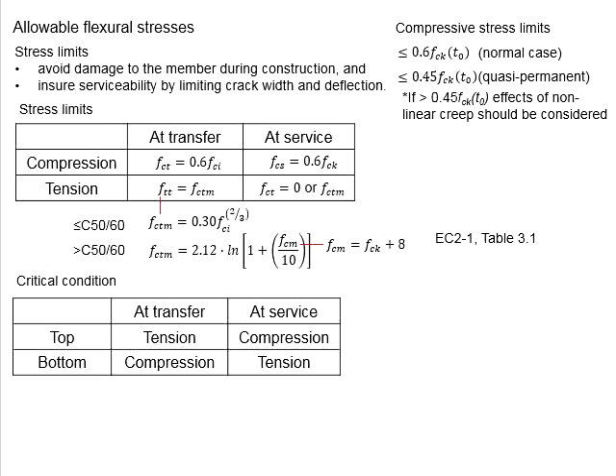Excessive cracks on the concrete will significantly affect the performance of the pre-stressed concrete structure. Before we look into the stress limit, these are the concepts of the compressive stress limit. There are two conditions: the normal case and quasi-permanent case. The quasi-permanent case represents conditions where the imposed load acts as if it's a permanent load. The differences between the two cases are the limits: 0.6 and 0.45.